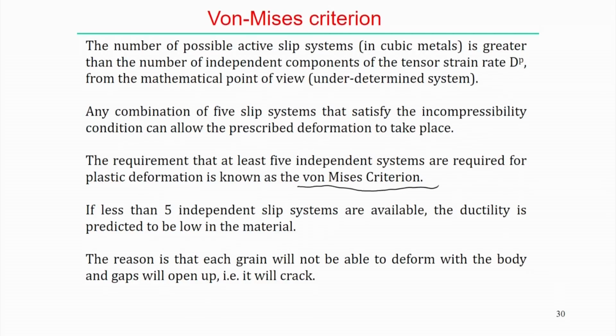Based on that, we can decide that at least 5 independent slip systems can be active at a time. If fewer than 5 independent slip systems are available, the ductility is predicted to be very low in that material, because in this prediction, if it is less than 5, it will violate the compatibility condition. That actually creates the crack formation during the deformation.